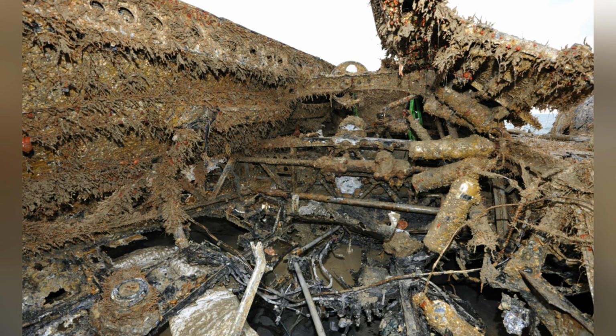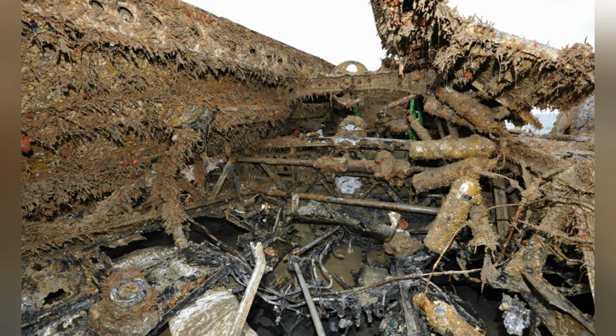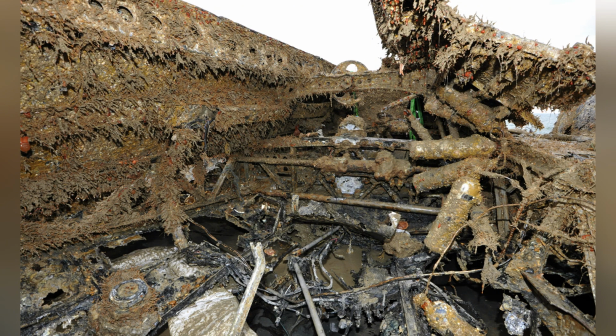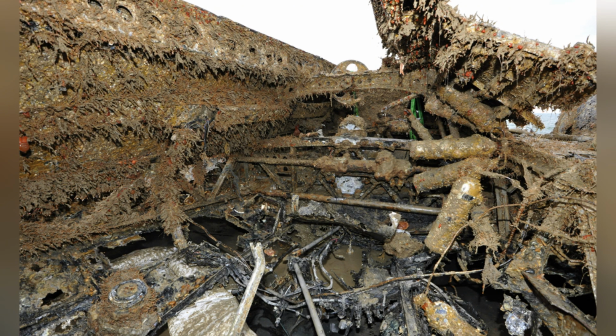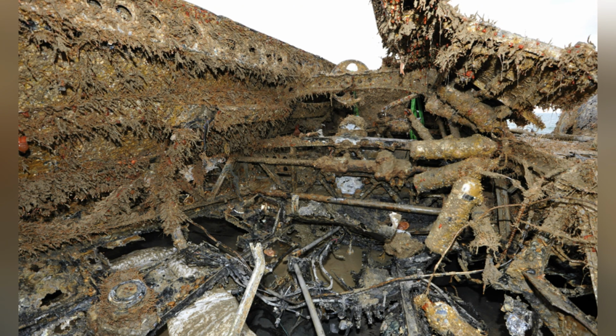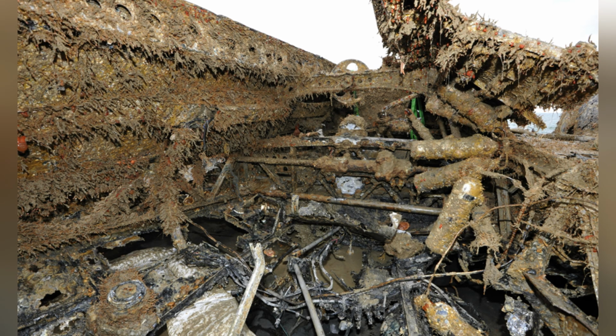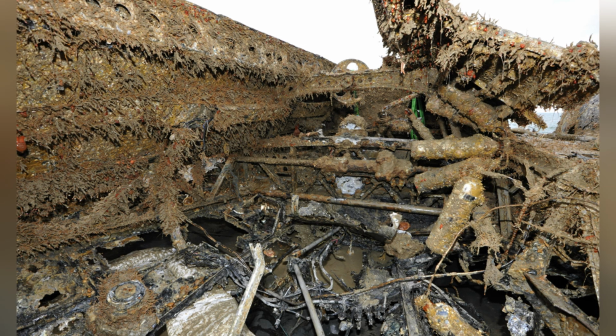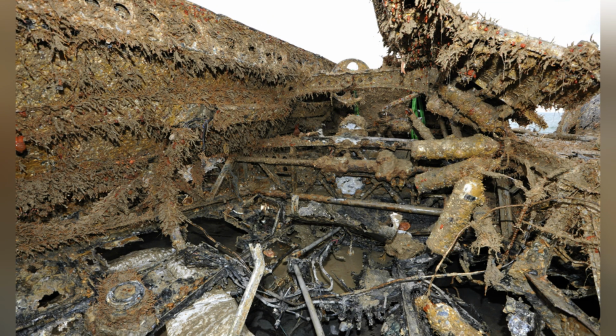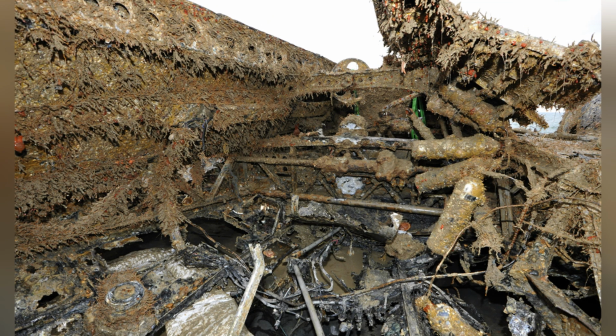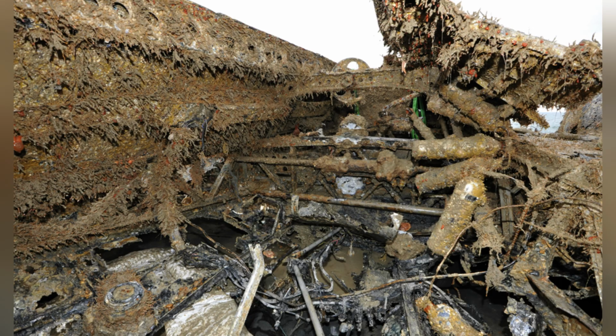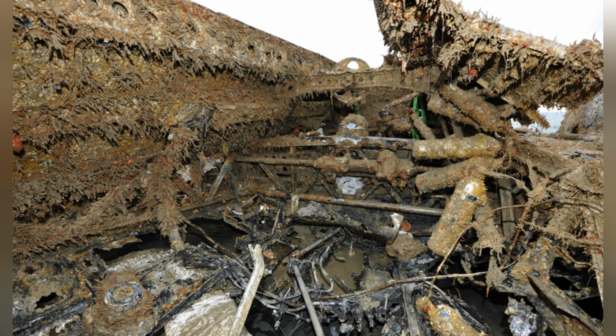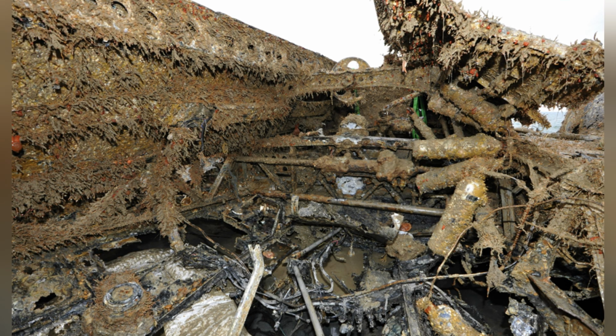The danger arises the moment the object is removed from the sea. If the airframe is exposed to air and allowed to dry without treatment, the water evaporates, but the chlorides remain trapped inside the metal. These salts then crystallize. The crystallization process exerts expansive mechanical pressure from within the alloy lattice. Simultaneously, the presence of oxygen accelerates the corrosion reaction.